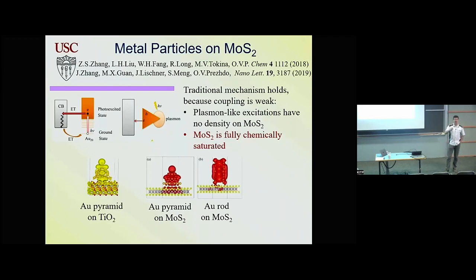from cadmium selenide or from titanium dioxide because they don't have any unsaturated chemical bonds. The surfaces are perfectly happy chemically, and in this case, this interfacial interaction is much weaker. Because it's much weaker, the importance of this photoexcited charge-separated state is much less significant. So in terms of transport, you would expect different behavior when you don't chemically bind the two subsystems versus when you bind them, and this depends on the substrate. If you're using a 2D substrate, it's going to behave differently from when you have a 3D substrate and a surface